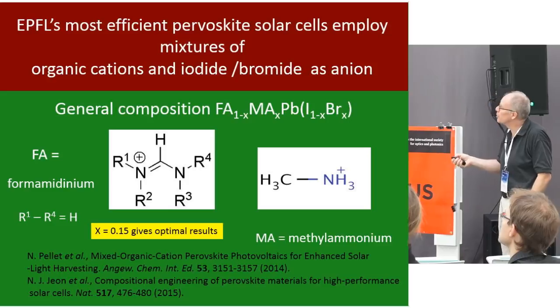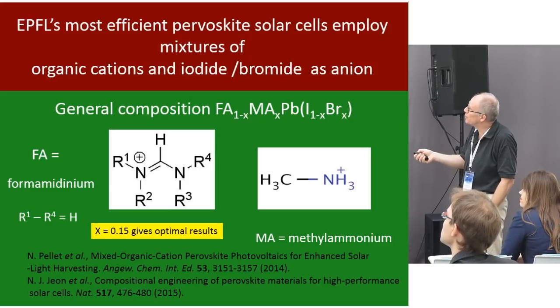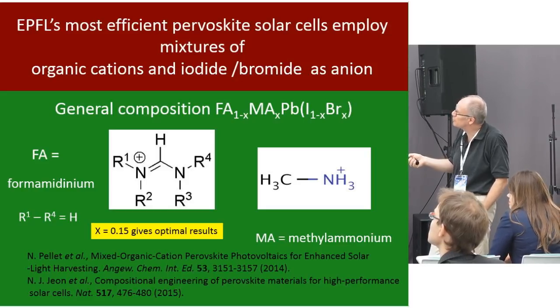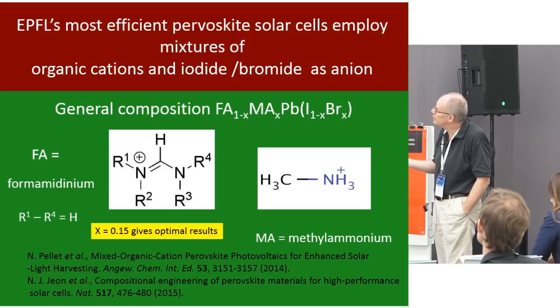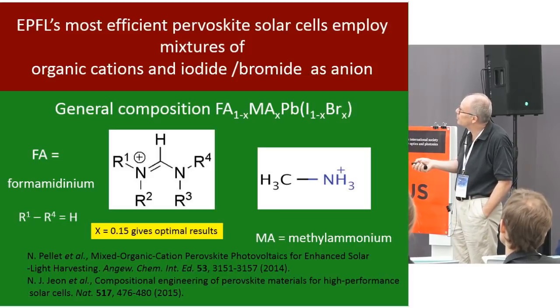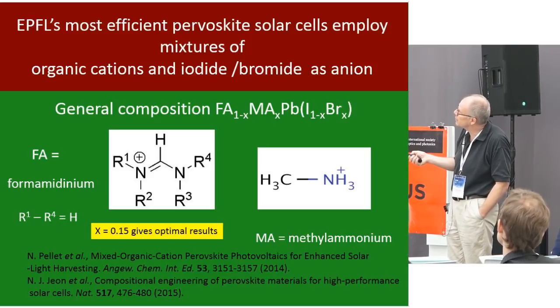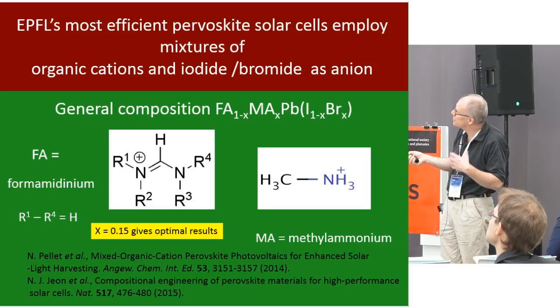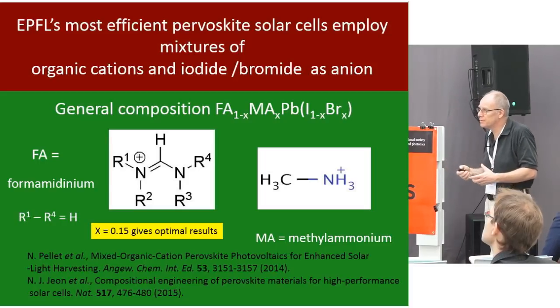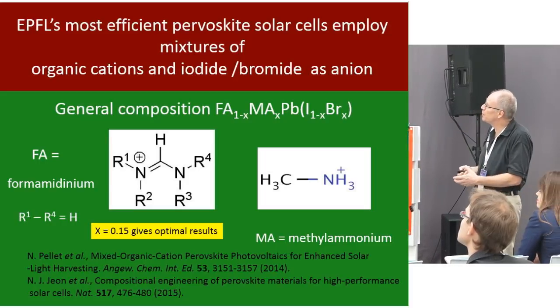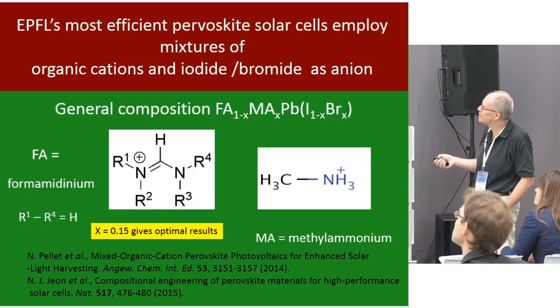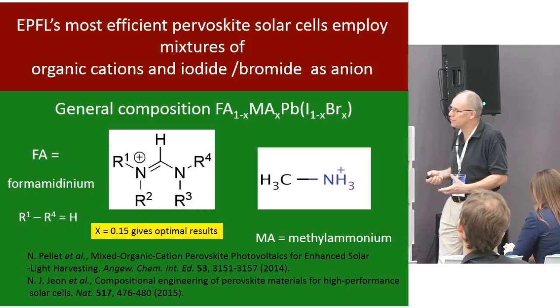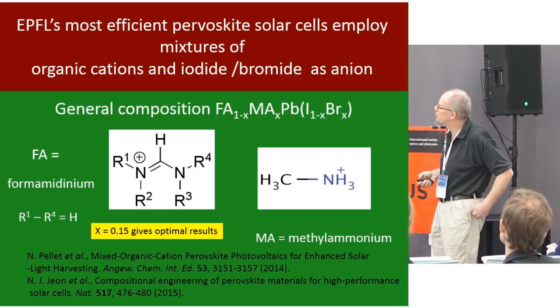You can also work on the cation. This was methylammonium. It's this ion here. You can also try to mix in formamidinium, and that's really what we want to have at the end. A little bit larger molecule. It shifts the band gap to lower values and also has other stability reasons better. Our goal is to have pure FA actually, but then very difficult to make that into a pure perovskite structure.